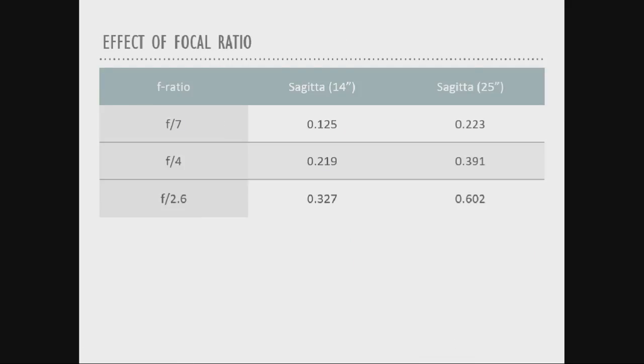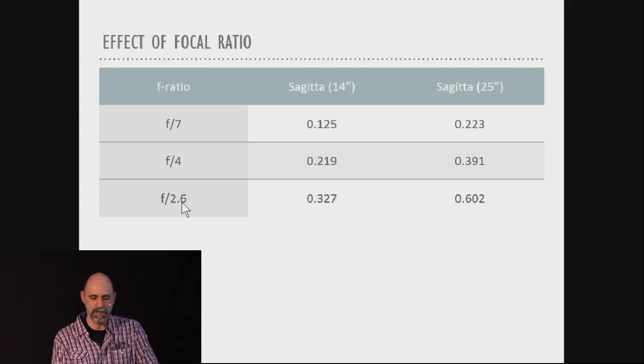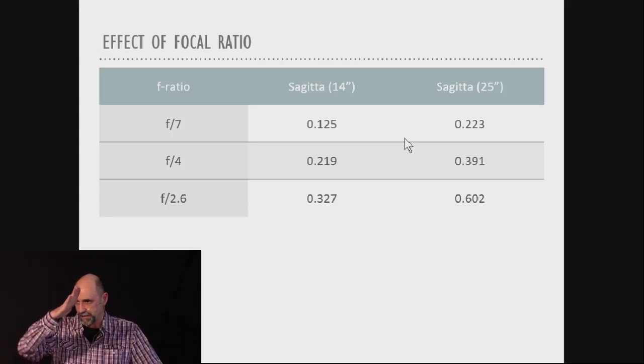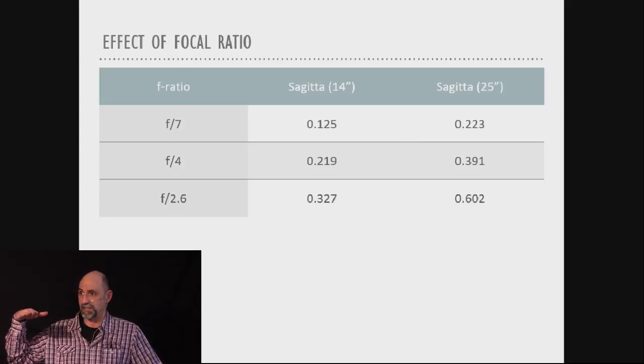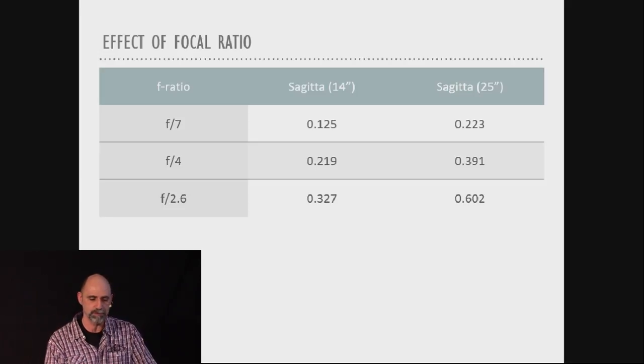If you consider focal ratio and how this impacts things as well, this table here lists a couple of common focal lengths, focal ratios, and the corresponding sagitta for a 14-inch, which is my personal project, and Mel's 25-inch. The sagitta is basically the depth of the curve of your glass. So it measures from the edge down to the deepest point. And so you can see how the faster your telescope, the deeper your sag is in your glass. And so for a 25-inch, the sag here is 6/10 of an inch.